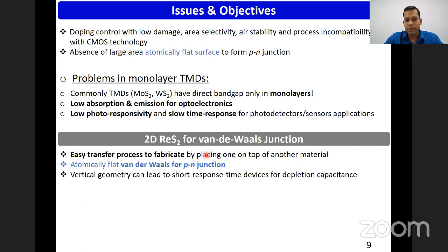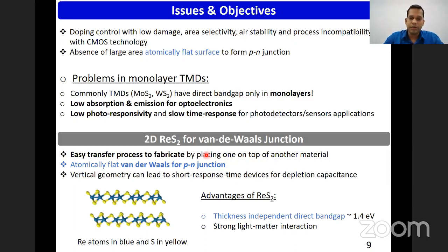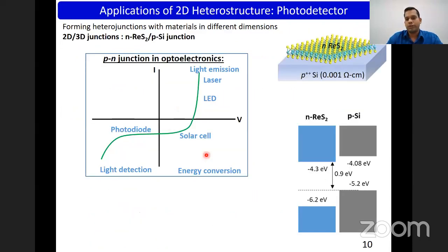So in that prospect, we can use two-dimensional rhenium disulfide, because it has a thickness-independent band gap. So even though we take a few layers of this material, it shows a direct band gap, and that will have high absorption. So it has a strong optoelectronic response. So that's why we select rhenium disulfide as an active material for optoelectronics.